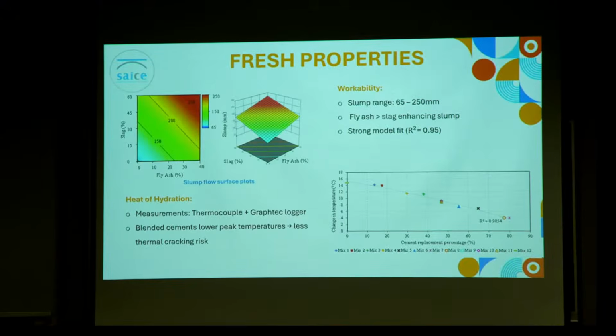Workability was assessed using the slump test. From the 3D surface plots, it was observed that both fly ash and slag contribute to increased workability, although fly ash contributed slightly more due to its spherical particle shapes. So how did I get all of this from the 3D graphs shown on the top left?